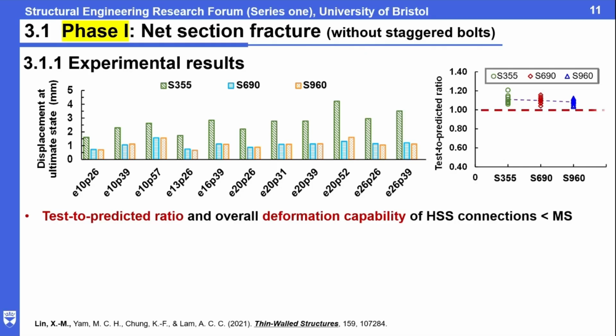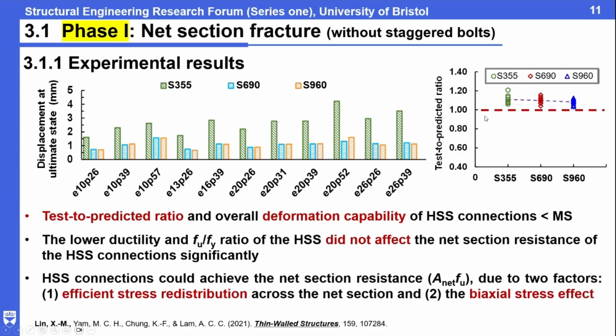And how about the test ratio? Let's see here. I drew a line across at 1. This value is the tested ultimate load over the predicted resistance, An·Fu. If this value is larger than 1, it means the strength across the net section can be fully developed to Fu, that is, the net section resistance can be achieved by the design model, An·Fu. If it is lower, it means the stress across the critical net section cannot be fully developed. That is the philosophy.